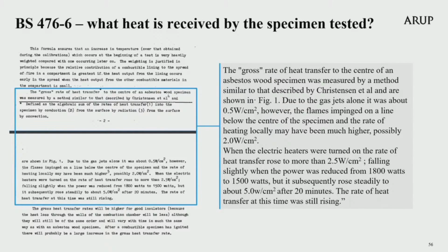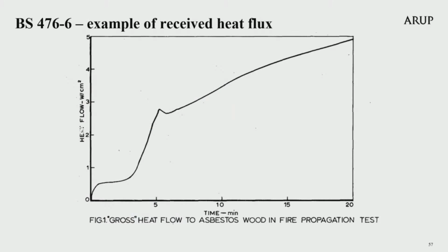On screen now, I've shown some text explaining the heat exposure measurements produced in this paper. This is for background information only, because the key information I want to present is the graph referenced within this text. This is figure 1 from fire note 710, and it shows the gross heat flow, the heat flux, received at and on the surface of the asbestos wood sample used in the test. The paper, for any fire scientists listening, defined the gross heat flow as the algebraic sum of the rates of heat transfer into the specimen by conduction, from the surface by radiation, and from the surface by convection.